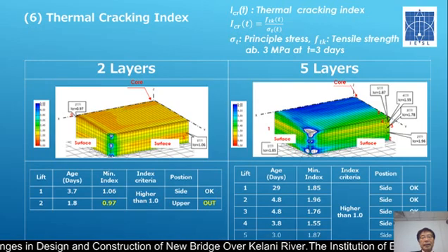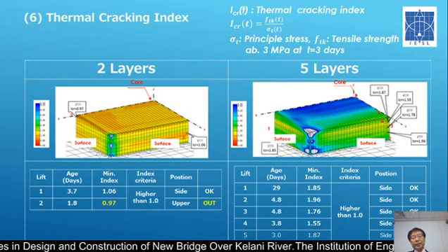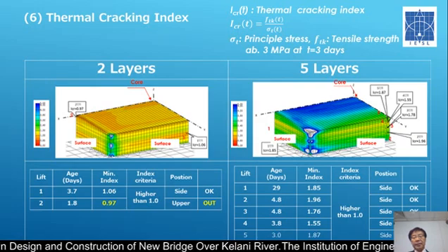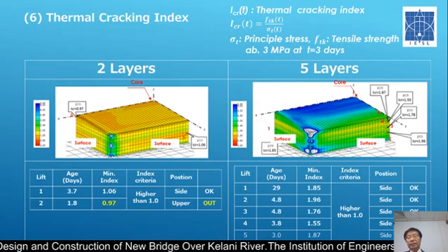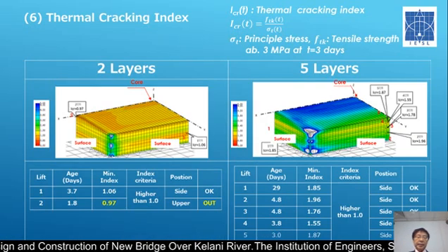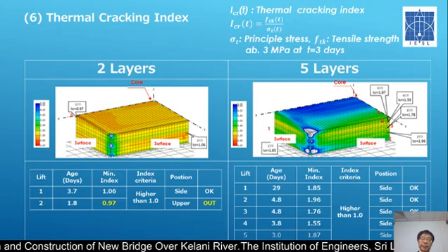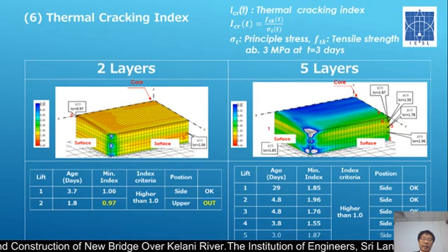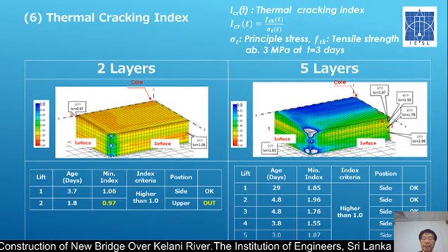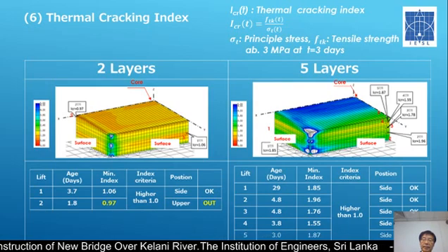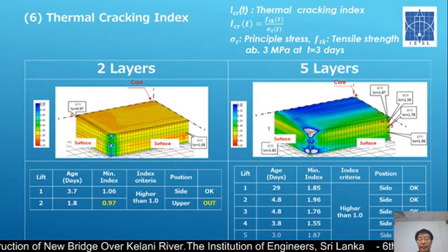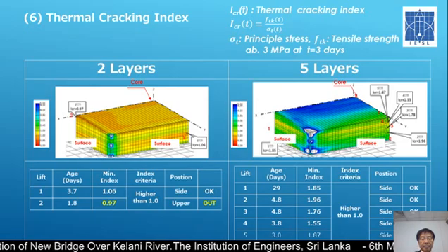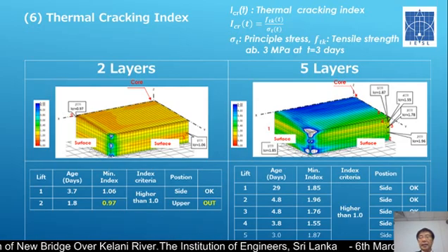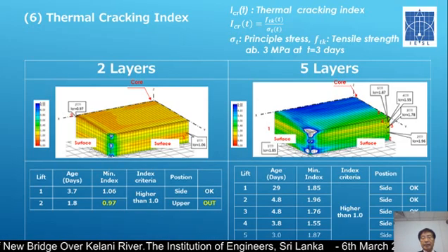After that, we have studied the crack index. That is, when the temperature changes, there are tension stresses due to the temperature differences, so we studied the cracking index. The 5 layer case has no theoretical cracking, whereas in the 2 layer case there might be some cracking.